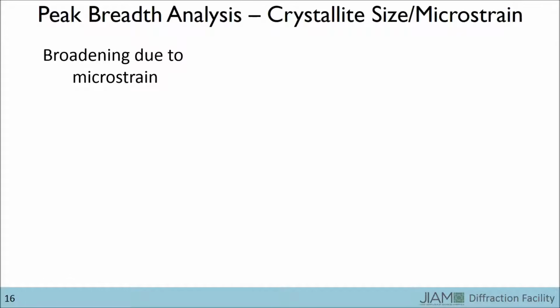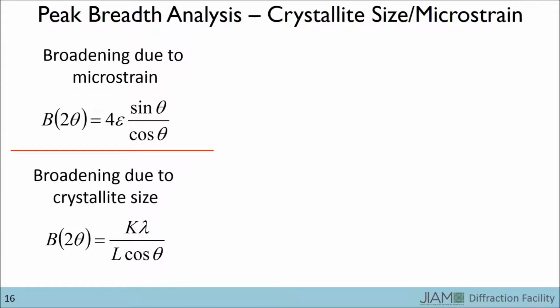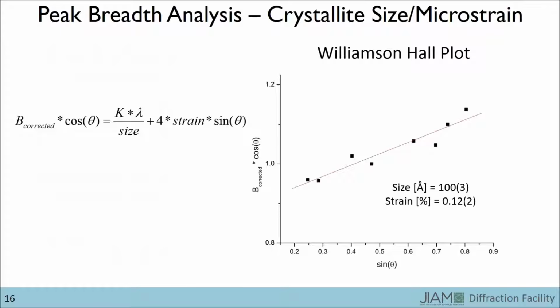Fortunately, there is an equation that also governs the effects of microstrain. The broadening is equal to 4 times the strain times the sine of theta divided by the cosine of theta. If we combine this with a broadening due to the crystallite size, we can make a Williamson-Hall plot. If we plot it so that the y-axis is the full width half maximum after having corrected for the instrumental broadening, times the cosine of theta, and put the sine of theta on the x-axis, then fit the data with a straight line, the y-intercept gives the crystallite size and the slope gives the microstrain. For this sample, it was determined that the crystallite size is approximately 100 angstroms and the microstrain 0.12%.